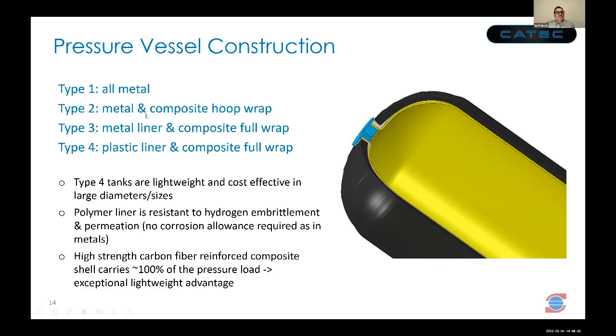So type 2 is metals with a composite hoop wrap. So the weight is reduced almost 20% going from type 1 to type 2. But the cost goes up a little bit because we are putting composites. And type 3 is a metal liner with a full composite overwrap. So the weight is significantly reduced, but the cost is also significantly increased. And the last one is type 4 that has a plastic liner, and the composite is carrying the full load. So the one that we are doing right now is this type 4 for very large scale hydrogen storage.